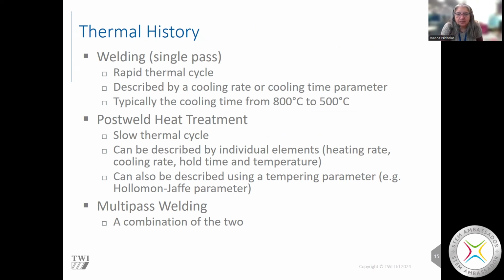It's a rapid thermal cycle, and it can be described quite easily by the cooling rate at a particular temperature, usually cooling rate at 1000 degrees C or 700 degrees C, or a cooling time parameter. Convention currently is that we use the cooling time from 800 degrees C to 500 degrees C as a definition of what the thermal history has been.